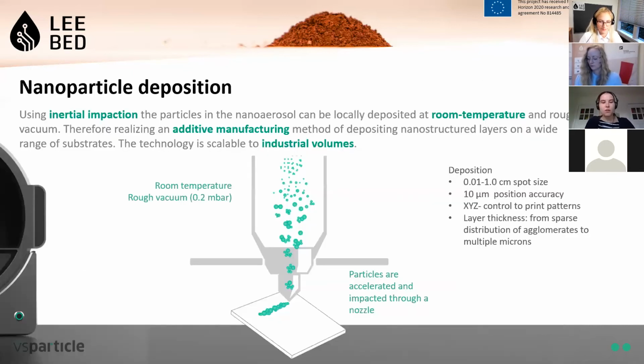The deposition unit: the deposition process is based on inertial impaction. The nanoaerosol that leaves the generator is transported towards the printhead with a nozzle. Due to the pressure difference between the nozzle and the vacuum chamber, the gas and the nanoparticles are accelerated, and the nanoparticles are then impacted onto the substrate.